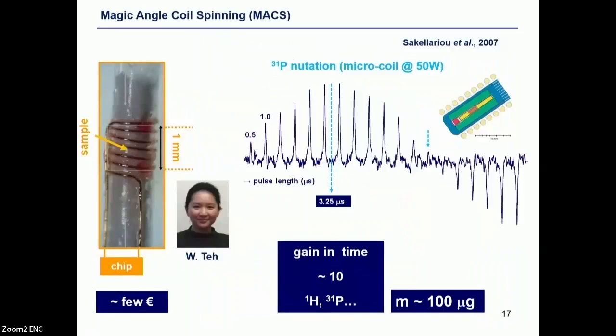So in order to analyze this kind of sample with very low mass, we decided to use a concept invented by Dimitris Sakellariou called magic angle coil spinning. The idea is to put the sample in a capillary here in the center and to wrap around it a microcoil, okay, which is here, and you see the characteristic size of the microcoil, soldered to a chip capacitor. And the ensemble of capillary, chip and microcoil is put in a standard 4 millimeter or 3.2 millimeter rotor, spinning at the magic angle in order to retrieve the resolution. And what Dimitris proved very nicely is that in this case, you increase the signal-to-noise ratio, mainly because the filling factor of your system is close to 1.